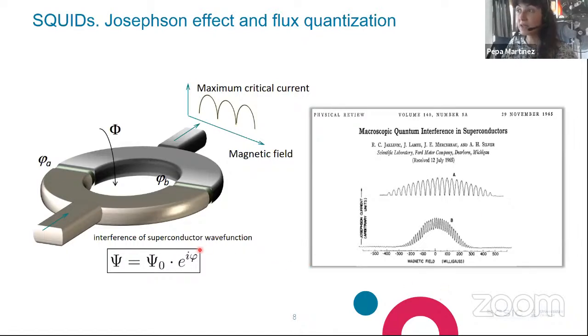Since the phase of the superconducting wave function describing a superconducting material must be single valued, this fact makes that the flux threading a superconducting loop can be only described in integer numbers of the flux quantum. And secondly, the Josephson effect. A Josephson junction, as you know, is a weak link between those two superconductors.